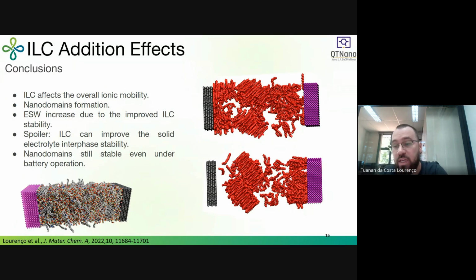However, when we have the charged battery, we can see that the nanodomains still exist in the liquid structure. However, the cations are here on the surface of the anode. And this can indicate to us that we have some formation of a stable solid electrolyte interface. And when we look at the experimental data, this is what they saw in the XPS and also in the SEM analysis. So even when we do simulations for confined systems for batteries, we can see agreement and contribute to the understanding of the experimental data.